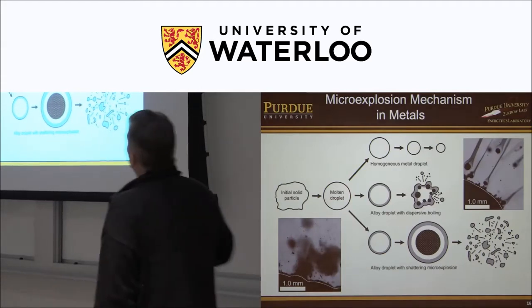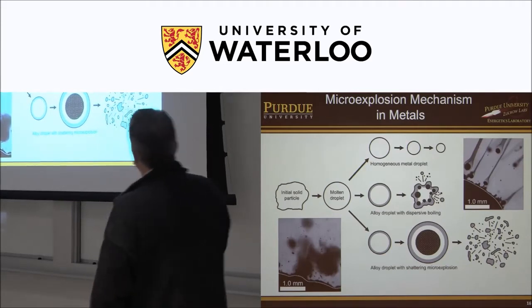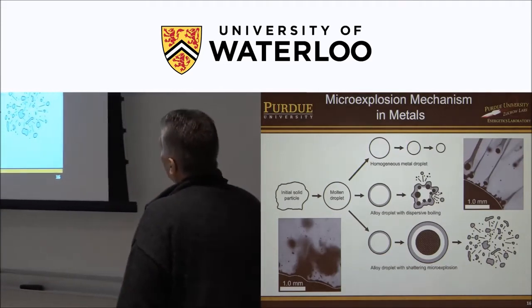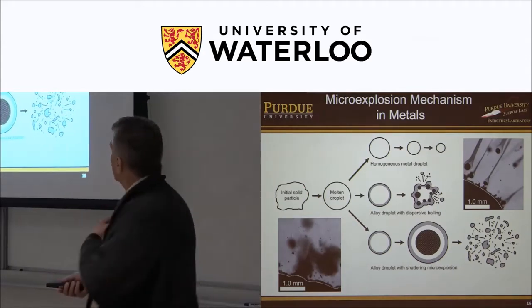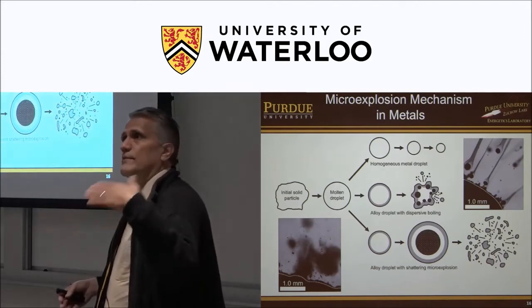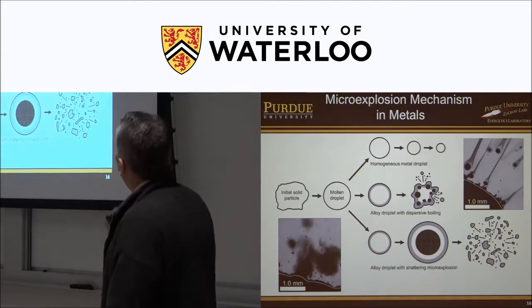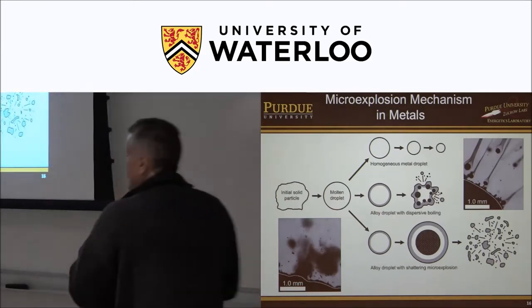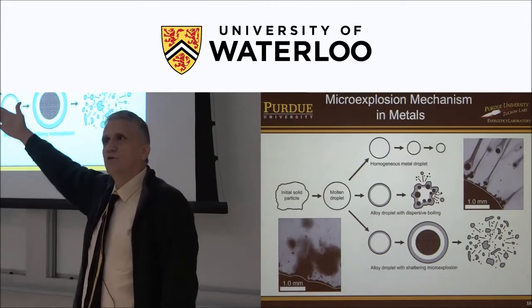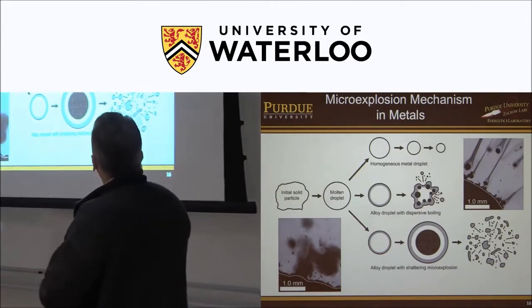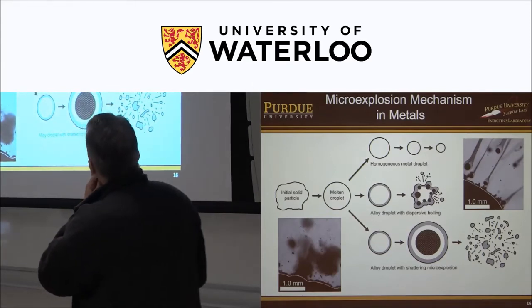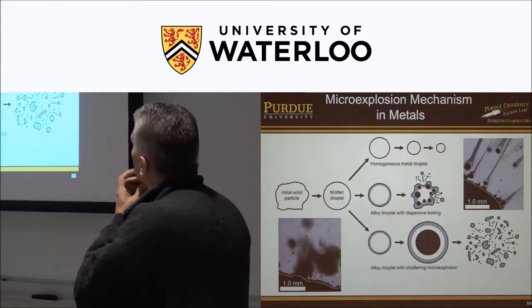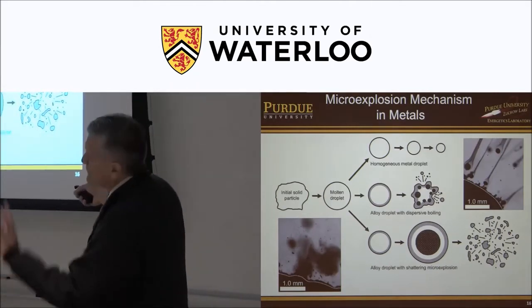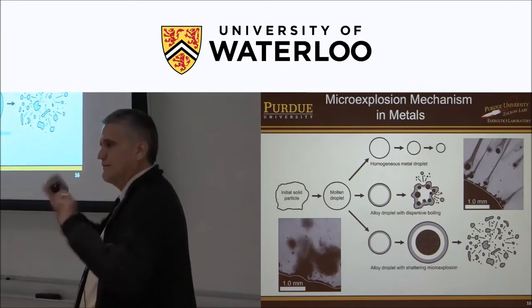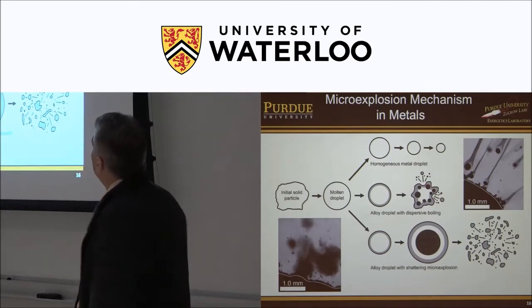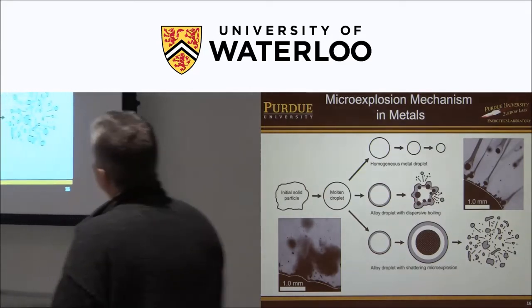If it's just a single component, say aluminum, that droplet could be consumed, becoming smaller, perhaps. If we have an alloy with a multiple component, the more volatile component, the component that boils at a lower temperature, in this case lithium, will boil off that surface very quickly. And the lithium near the surface doesn't have to diffuse very far, and so it diffuses and goes to gas. And that leaves the aluminum that's not boiling yet. So you have kind of a shell here of aluminum. And under certain conditions, and if you're watching enough of these high-speed videos, you see almost like little volcanoes coming off that droplet. We call that a dispersive boiling type of phenomena.